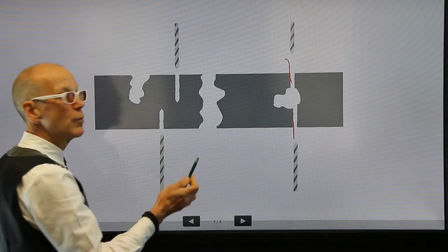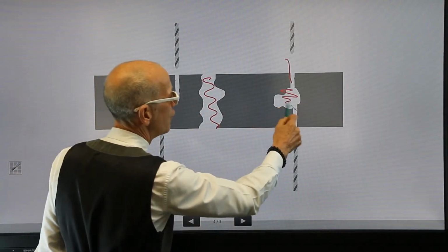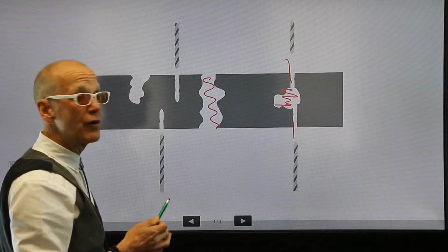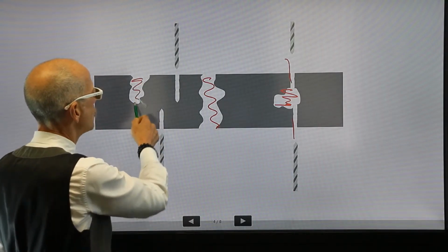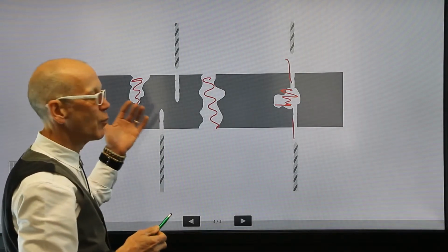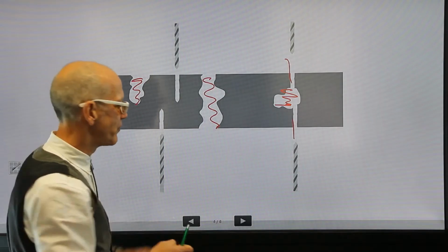Now, if you do the impregnation after machining, you'll still fill this, and now you'll fill this leak path as well. The reason you want to do it prior to finishing is you want to fill up all the porosity before you do the plating or painting. Otherwise, you could end up with outgassing or other blemishes that really don't look so nice.